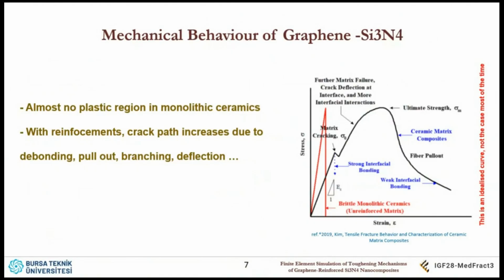I couldn't find any tensile curve for silicon nitride or its nanocomposites, but a schematic plot is given by Kim et al., which tells that monolithic ceramics have almost no plastic region. However, their composites have some plastic region. This is a bit exaggerated. It wouldn't be the same level of ultimate strength; it would be a bit lower. But anyway, with the addition of some fibers or nanoflakes, the crack path increases due to mechanisms like debonding, bridging, branching, etc.